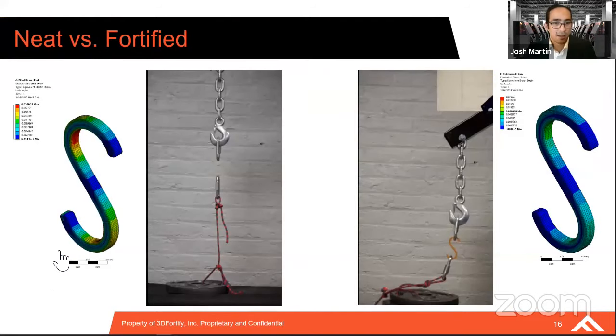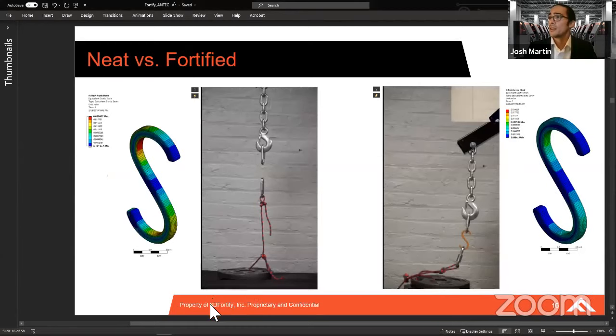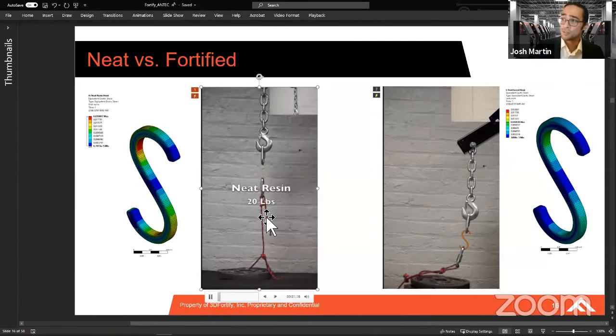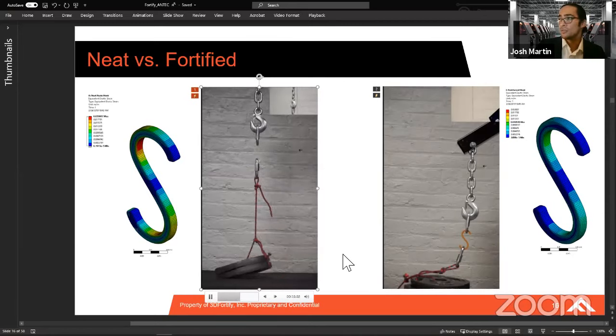Okay, and so I might have to pull out this again out of the full screen mode. So bear with me one more moment. What we have here is essentially a neat polymer on the left versus a filled and aligned part printed using Fortify. It's the same resin chemistry. What you'll see on the left here is under about 20 pounds of load, once the part is jacked up, you'll see very brutal failure.